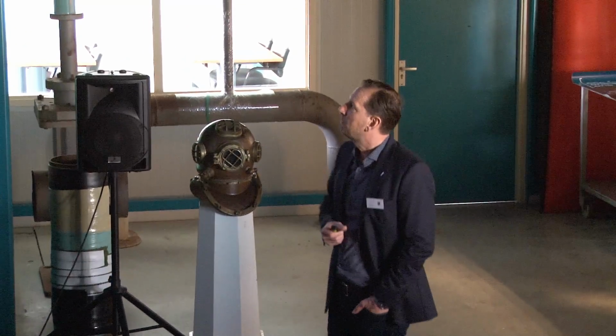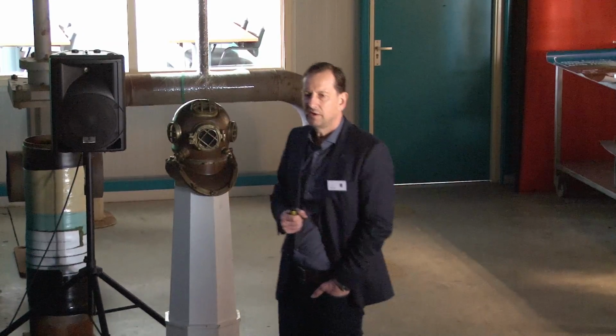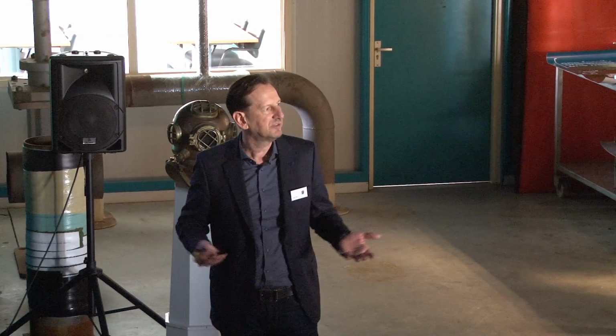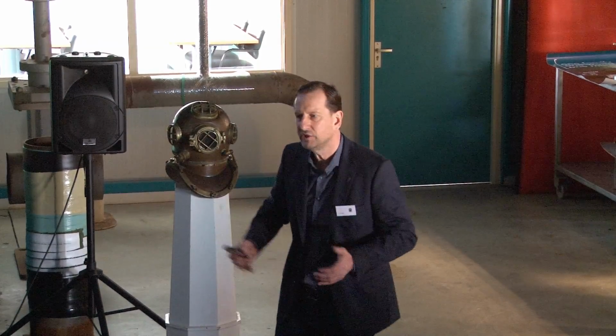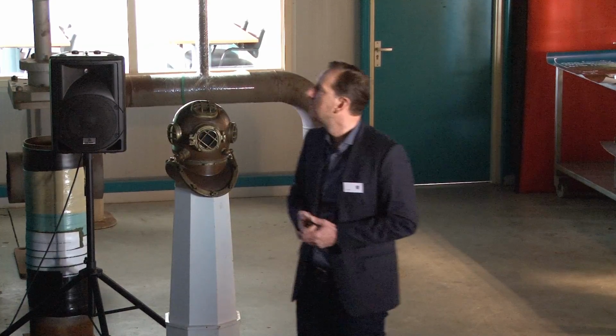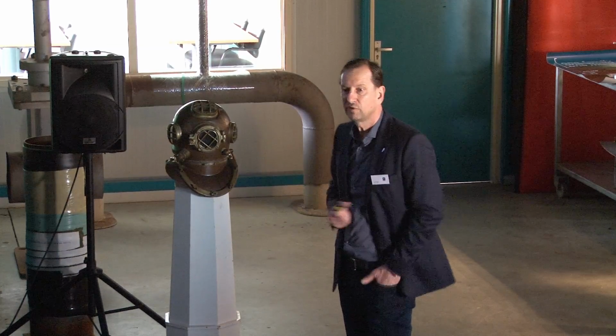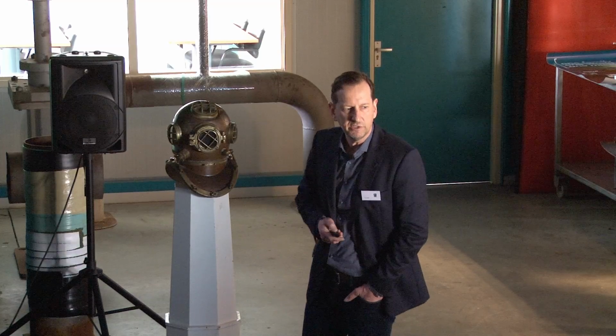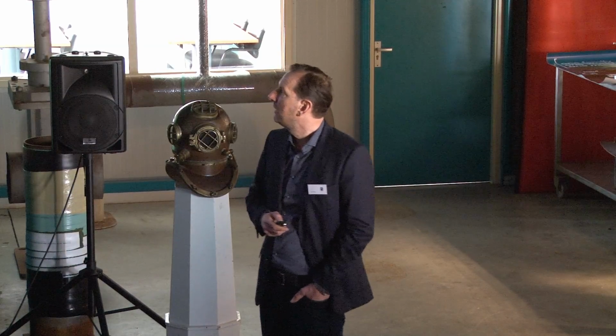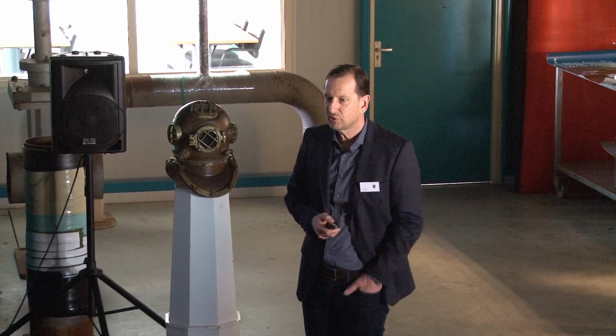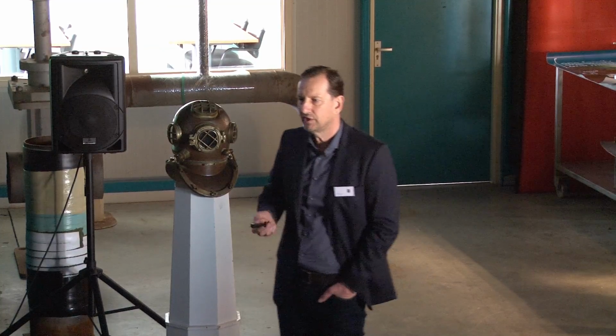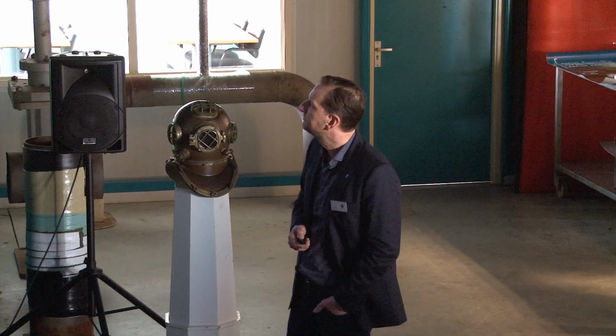How do we apply it? At minimum, substrate preparation. You always have to refer to the specific standard. This is St2, St3. St2 is by hand, St3 is by mechanical tools. Cleaning, of course, because we don't adhere on greasy substrates. Dew point, we don't adhere on wet substrates, but we have to check it. It's not different from traditional coating systems.